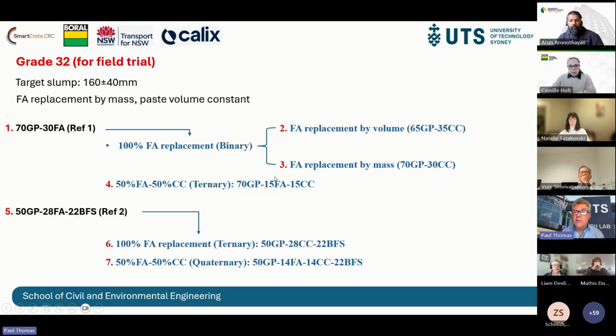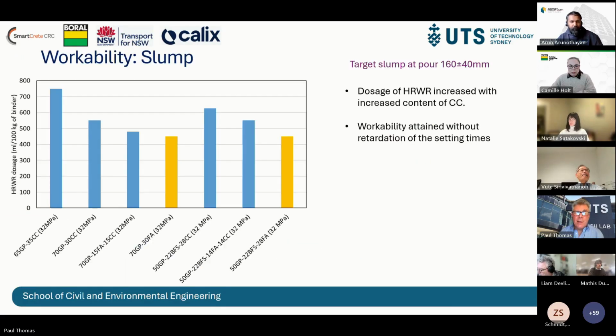We also looked at ternary blends where we partially replaced the fly ash, and that was replicated as well in the ternary blend with blast furnace slag, where we also 50-50 substituted the fly ash. This was after a lot of work developing and working out how to get the workability right and what sort of admixtures to use. We ended up with these 5 mixtures, and the aim was to produce a grade 32 megapascal concrete for pavement in a field trial.